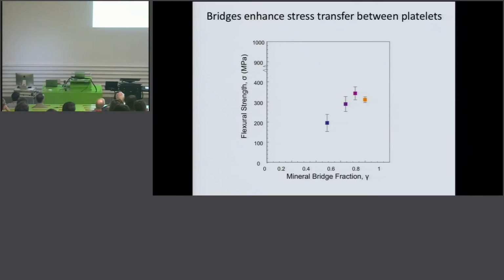It's basically the size of a normal seashell. You will see that it's very shiny, and the reason for being shiny I can answer in your questions. But that's the scale that we're able to produce them. But this is still with 40% of platelets, 60% of air. So in a second step, what we do is to press on this material so that we densify and increase the volume fraction of platelets up to 95 volume percent, and then we get something like this. This is just smaller because we used a smaller mold, but this is the artificial nacre that we are creating.